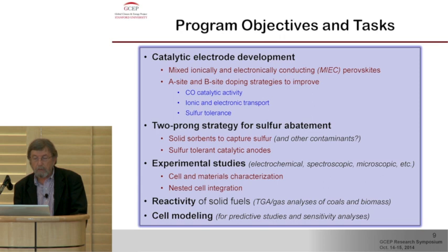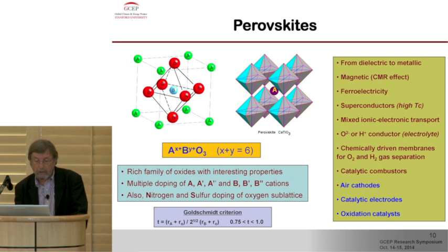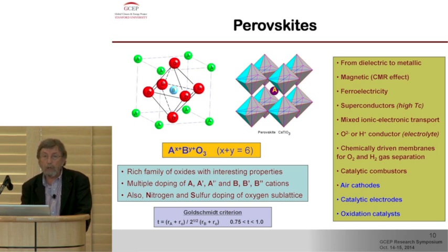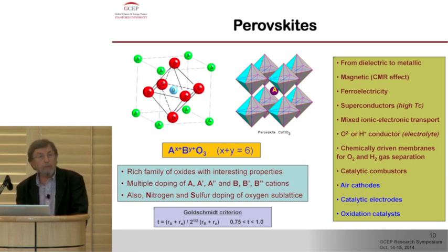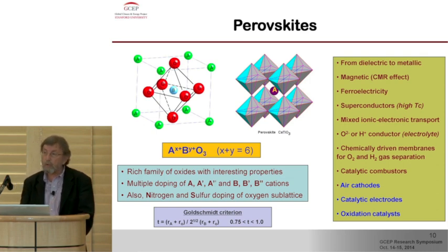So what we're looking at, perovskites, these materials are very versatile and give us an opportunity to tune ionic and electronic transport properties as well as catalytic activity. They also provide us with doping strategies on the A-site and the B-site, where you can have multiple dopings, as long as you maintain or satisfy the Goldschmidt criteria to maintain the perovskite structure. It provides a lot of flexibility in terms of tuning properties.